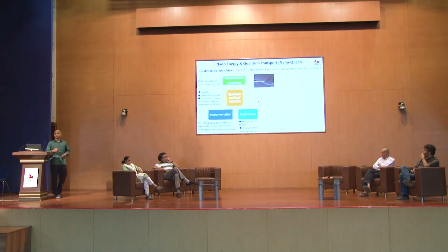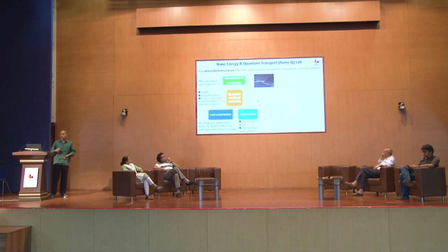And some recent results, like Pawan said that we should show some breakthroughs from our lab. I don't know whether they are breakthroughs or not, but at least the student got either a paper or a patent. Okay, so this one is, we developed a new growth promoter for these transition metal dichalcogenides, where you see here is a monolayer MoS2. It is conformally coated on a silicon, even highly structured material, where the radius of curvature is around 20 nanometer, and we are able to make the conformal coating even at that high curvature. We got a patent on that growth promoter.